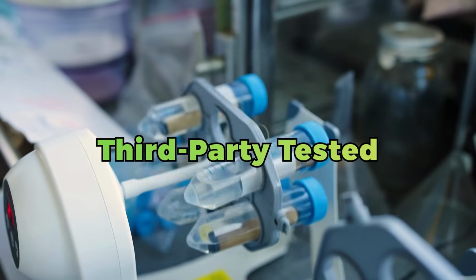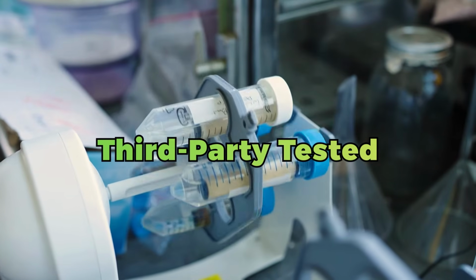High Tech Coatings has done third-party testing that shows epoxy creating approximately twice the bond strength of polyaspartic. We're talking about a chemical bond that's often stronger than the concrete itself. Polyaspartic bonds well, but it doesn't create that same deep wicking bond that epoxy achieves. The winner here, epoxy.